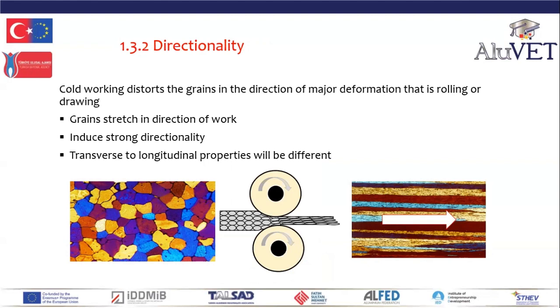Cold working distorts the grains in the direction of the major deformation, that is rolling or drawing. So by cold working, because we're working the metal and it is moving in a direction, we are introducing directionality into the grains of that metal. When you roll, you reduce the slab thickness as the metal volume remains the same. The rolled sheets grow in length. This results in the grains stretching, slipping, and elongating in the direction of work. This introduces strong directionality.